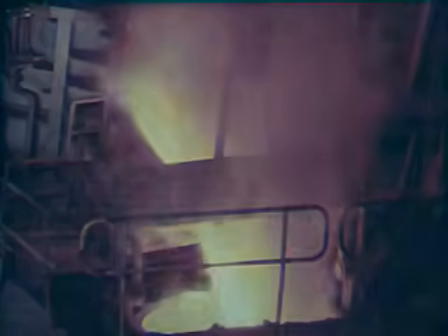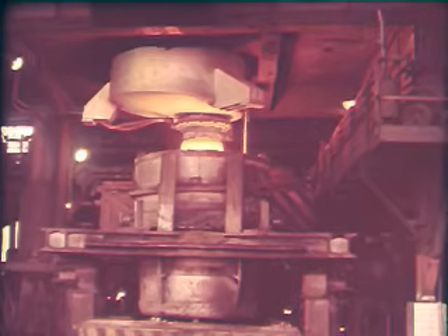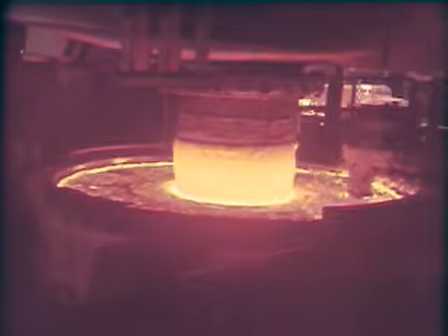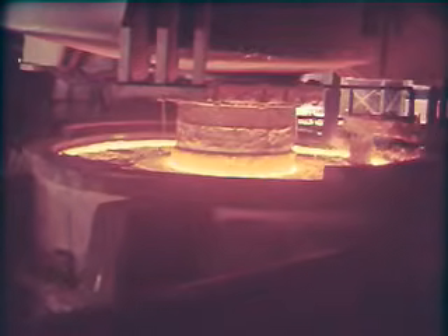With the steel composition checked and the melt completed, the furnace is tapped into a transfer ladle. The ladle is then moved into the vacuum degassing plant, where the molten steel is processed to remove unwanted hydrogen and oxygen which would otherwise be trapped in the steel and form harmful inclusions or defects. Further alloying elements can also be added under vacuum at this stage to ensure the steel matches the required specification.